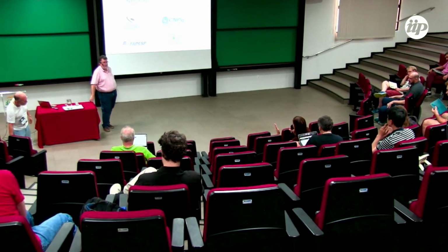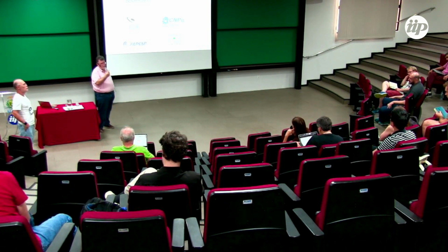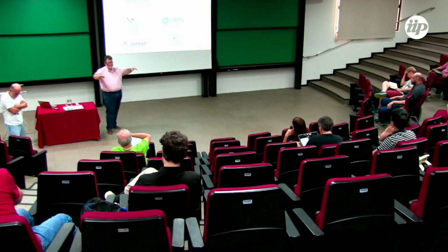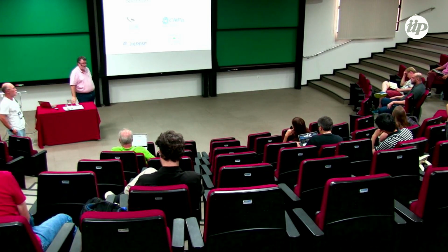Questions? Mariana? The distribution of the impurities, whether it's random or periodic, does it matter at all? It probably is random, because it is a very small quantity, 0.1, one vanadium atom per 1,000. And an important characteristic of the homogeneity of the sample is the width of the transition. This transition of the sample is very thin. With a distribution of impurities, different parts of the sample have different Néel temperatures, creating a broad transition. In this sample, the single crystal has very homogeneous behavior. And different parts of the sample show the same behavior, the same temperatures.